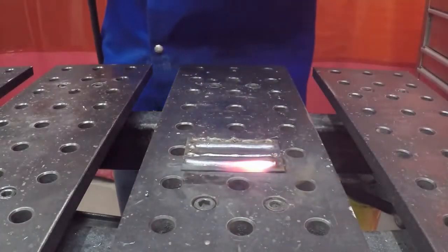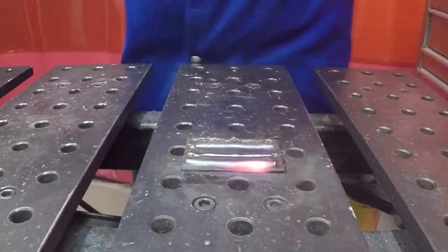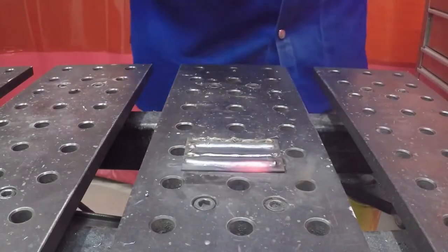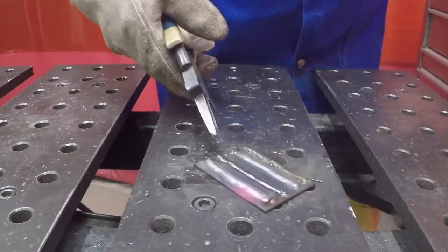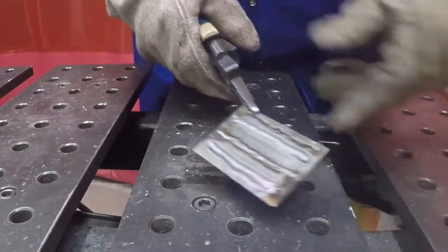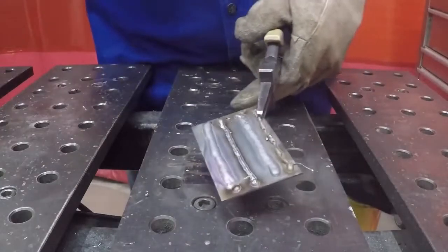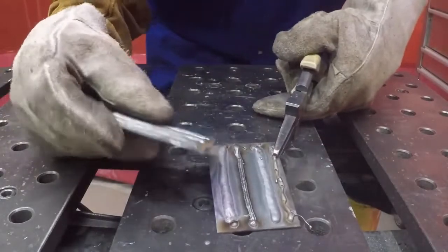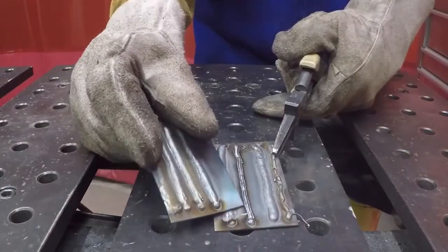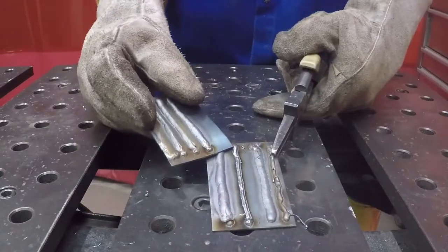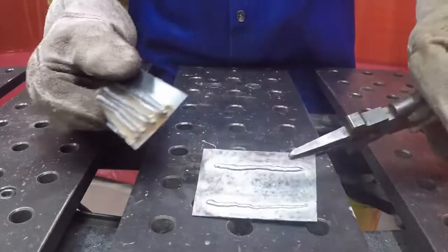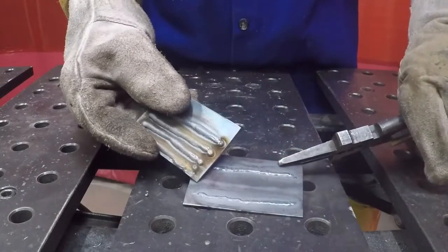So these are the two most common problems I see when students are doing the Weld Lab back here. When they first start, they're a little intimidated by the welder and they tend to go really, really fast. And when they go really, really fast, we get this weld that looks like this. It's just a string of wire that came across the top. And if we look on the bottom, there is no penetration at all.